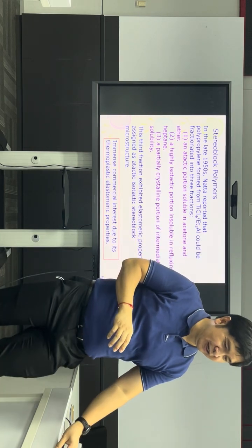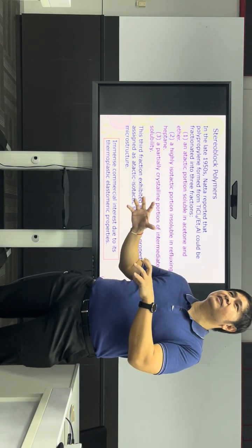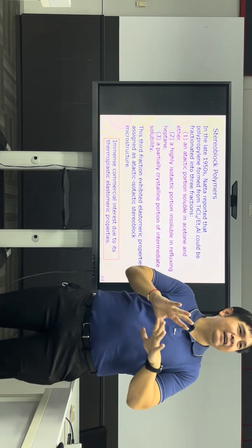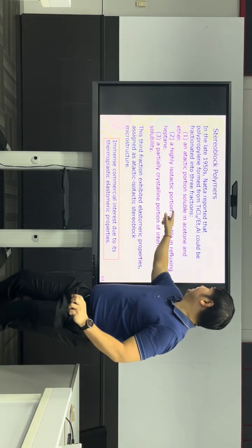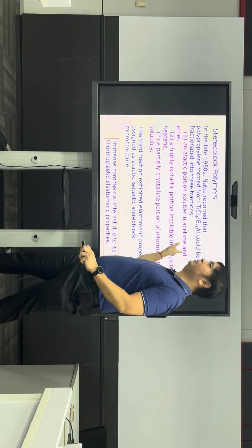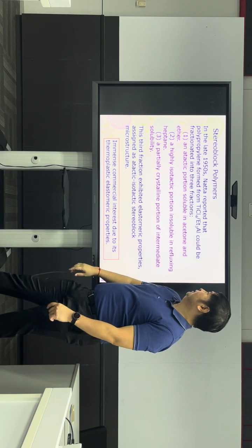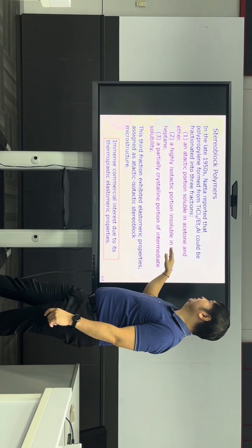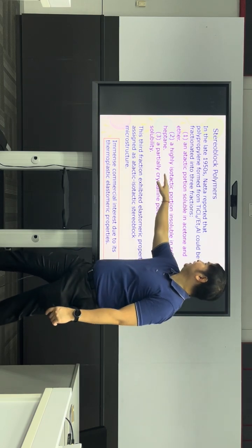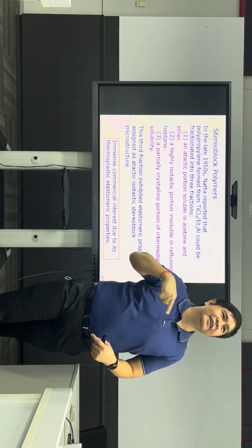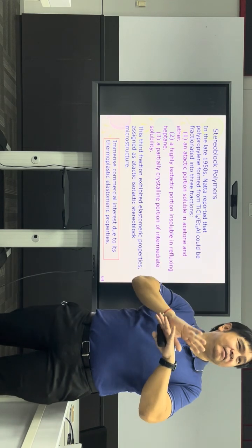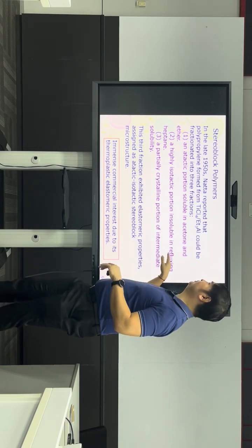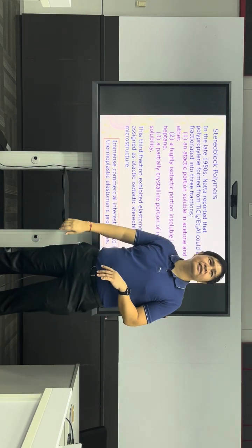Remember I told you when you have crystalline, the polymer is strong, right? Atactic, the polymer is not strong, it's soft and soluble in many organic solvents. So the atactic part is soluble in ether or acetone. But the highly isotactic portion will be insoluble in mostly anything. If you have heptane and you reflux it in heptane, some of it will dissolve, some of it is still there. What is insoluble in refluxing heptane is called the isotactic portion at the time.